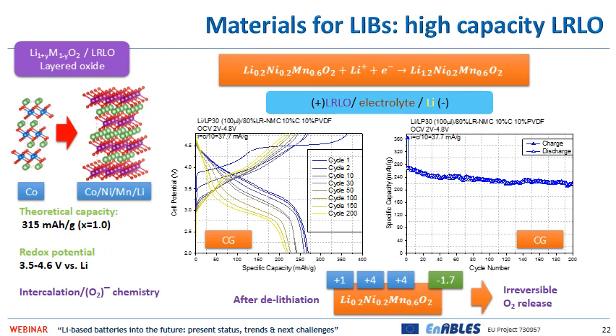The last material that we are reviewing is the lithium-rich layered oxide. This family of materials tackles the challenge of high-capacity cathodes. In fact, this material is able to exchange one full equivalent of lithium, and thus breaking the wall of the theoretical capacity above 300 mAh per gram for a positive electrode material. This kind of materials is formed starting from lithium cobalt oxide by removing cobalt ions and substituting them with a blend of transition metal and lithium. In this way, the same structure of lithium cobalt oxide becomes more flexible and able to fully intercalate one equivalent of lithium.